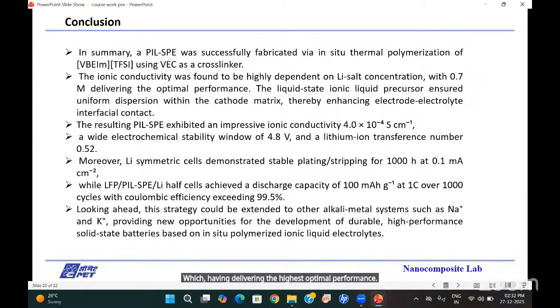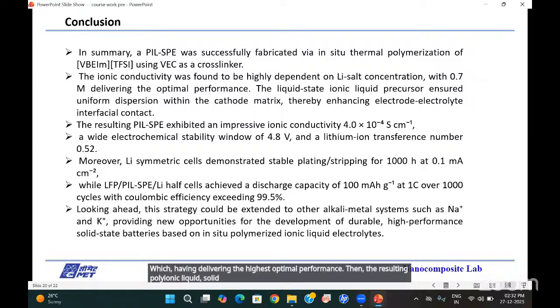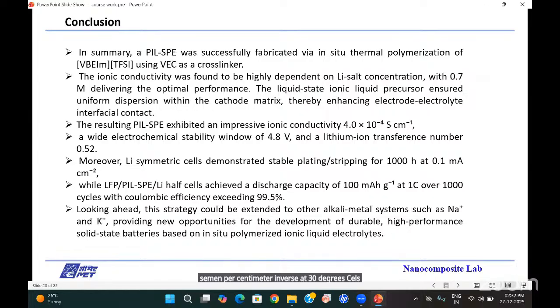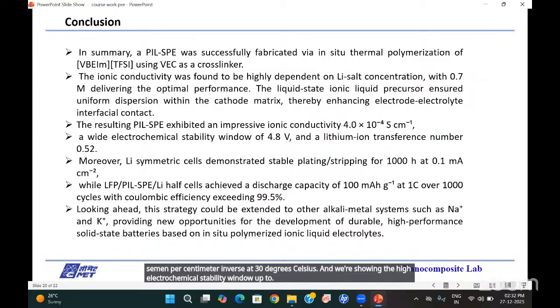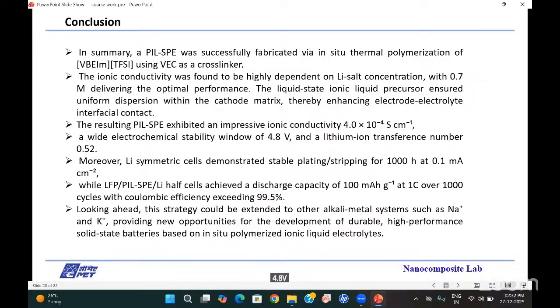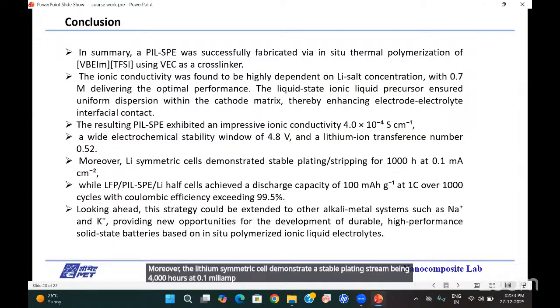Then the resulting polyionic liquid solid polymer electrolyte exhibits a higher ionic conductivity of 4.0 × 10^-4 Siemens per centimeter at 30 degrees Celsius, and we show a high electrochemical stability window up to 4.8 volt and a high lithium ion transference number of 0.52. Moreover, the lithium symmetric cell demonstrates stable plating and stripping for 1000 hours at 0.1 milliampere per centimeter squared, and our battery performance is